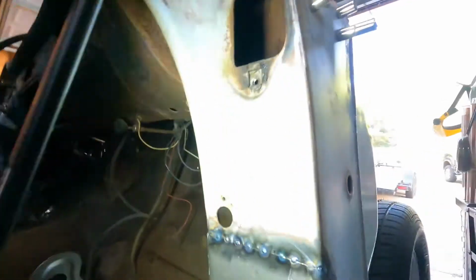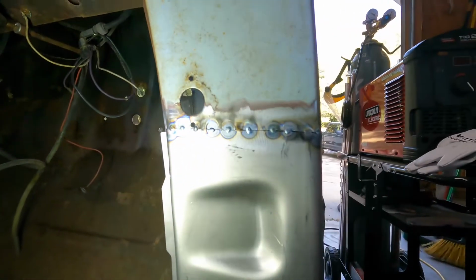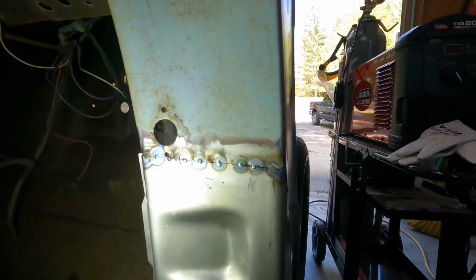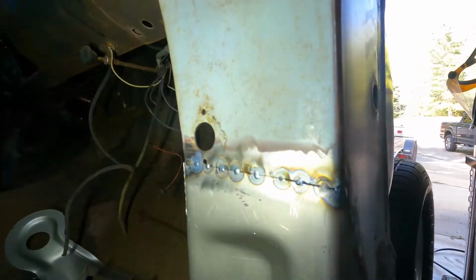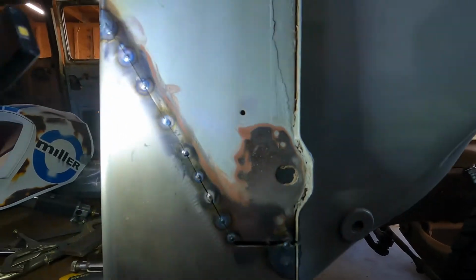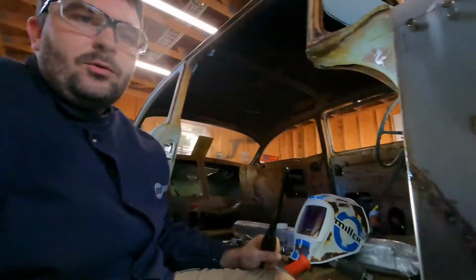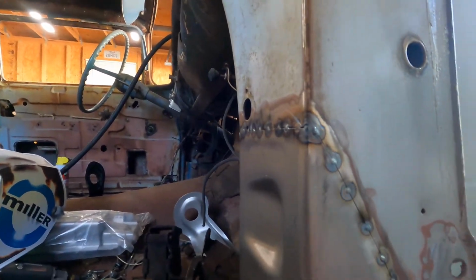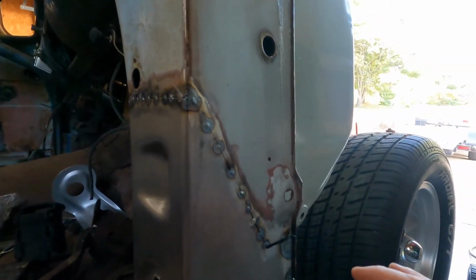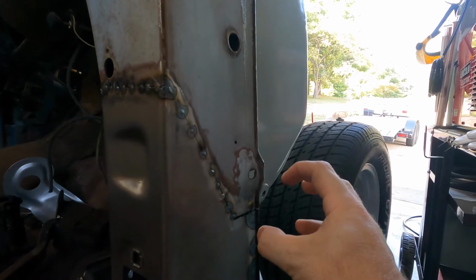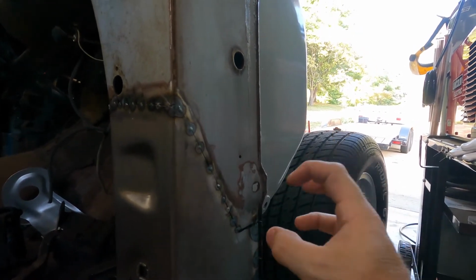I thought I'd stop for a minute and show you around the tacks that I've got going on. About every 1/2 of an inch is the spacing on these. If they stick up a little bit proud, I knock it down with a hammer and dolly, as you saw, just trying to keep everything flush. As the weld puddle cools, it'll actually squeeze the metal in. So you want to hammer and dolly those and let it relax, relieve the internal stress in there. So that's what I was doing, just hammering on the tack to relieve that stress, because the molten metal, as it cools, it constricts, contracts, and cools smaller than the liquid puddle, and it'll actually pinch things in.